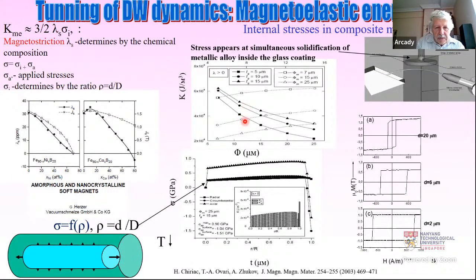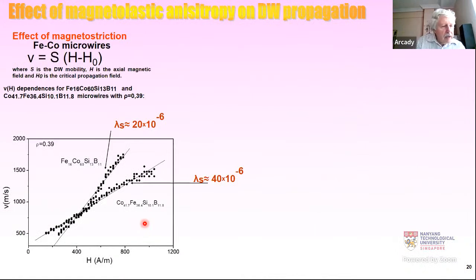This picture is a little bit complex, but the most important thing is the dependence of internal stress on the radius of the microwire. These stresses are mostly of axial origin. So the axial one is the highest, and only at the interface between glass and metal does it change sign. And the strength of these internal stresses can be tuned by the ratio. The thicker the glass, the more volume of glass we have, the stronger these internal stresses are for a fixed diameter of our materials. In this way, we can tune the hysteresis slope of our materials by changing the ratio between the metallic diameter and the total diameter of the microwire, and then even the magnetic properties. But I will show you also that the domain wall dynamics is also affected by these properties.